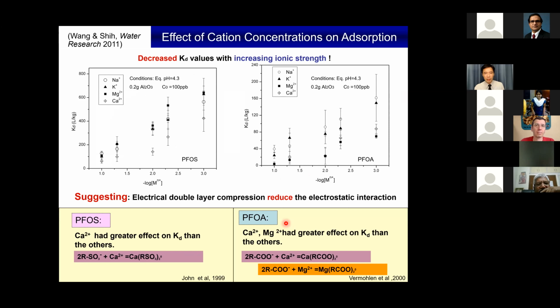Also, we looked at how different kinds of cations may affect the adsorption behavior. We find that with calcium, overall, when you have higher ionic strength, more ion concentration in the solution, then the adsorption of this type of compound will be much less. That's totally fine. But particularly when you have relatively higher calcium, the adsorption will be much less, because the mechanism we found is that calcium has a kind of bridging effect between different PFOS molecules, and that keeps them from being adsorbed.